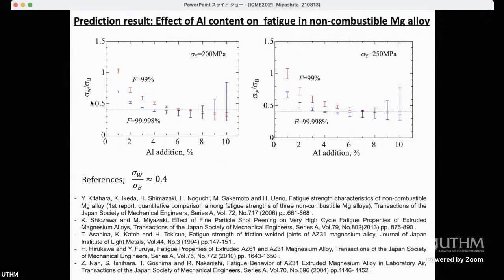This fatigue strength ratio is the ratio between the fatigue limit, actually in this case fatigue strength at 10⁷ cycles, and tensile strength. As you can see from this figure, the fatigue strength ratio decreases with increasing aluminum content until 4% of aluminum content. However, above 4% aluminum content, the fatigue strength ratio becomes almost 0.4. When we check the fatigue strength ratio reported in previous papers, in most cases they report that the value was 0.4. So that means our prediction is quite reasonable.